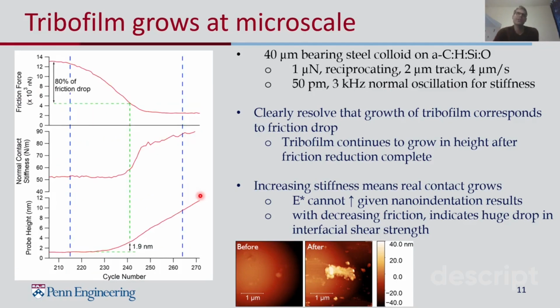We can learn one additional thing by zooming in on the area where the friction drop occurs. So this is from cycle 200 to 300 or so. And what we can see is when the friction drops about 80% from its maximum value, the change in the probe height is only about 2 nanometers.